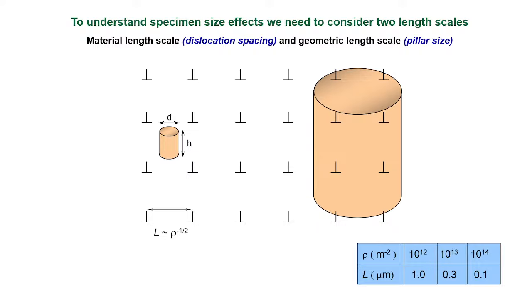And then if you're in between, right, then all the statistics of dislocations and the activation energy, the stresses needed to activate dislocations, all those come into play. So you get a distribution of sizes in this range. You get one strength in this range and another strength in this range, which is sort of deterministic, and here it would be statistical, probabilistic.